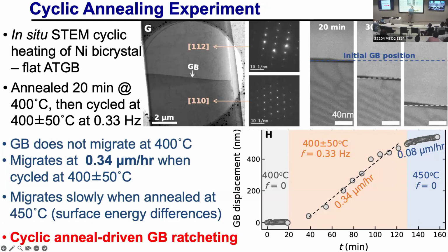You get a migration rate of 0.34 microns per hour. Not a lot, but I don't know where the maximum rate is. And interestingly, if you go and hold at the higher temperature, you still get some small amount of growth. But that's just because these two crystals have different normals, and the surface energy of this is different than the surface energy of that. So the difference in surface energy will still give you some migration, some driving force in one direction. Okay. So I think it's a very nice experimental confirmation of the migration.